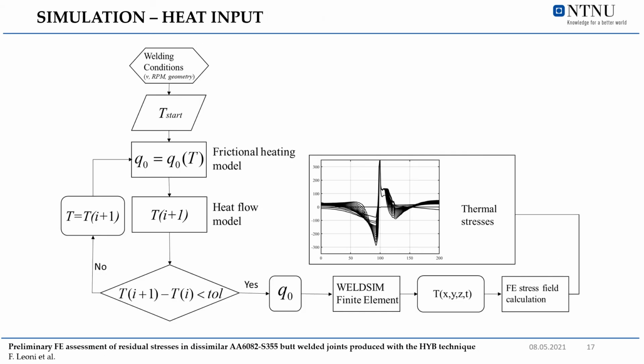In order to run the simulations at 3 welding speeds, the heat input had to be assessed, and this was done considering a heat generation model developed for butt welds of similar aluminum joints. This model considered the welding conditions and calculated the corresponding heat generated by the interaction between the tool and the workpiece, and by the filling of the hot material. This model was written in MATLAB. Once the heat input Q0 was calculated, the value was sent to the finite element code that assessed the thermal history and finally the thermal and residual stresses.